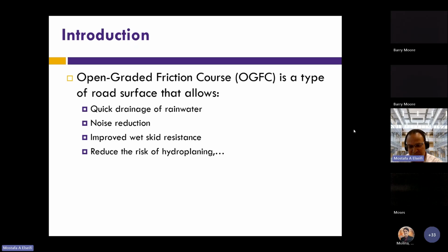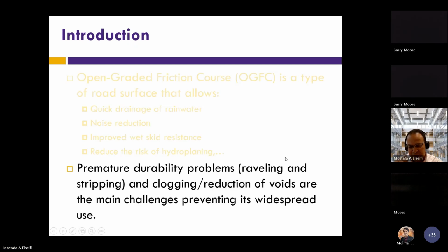However, in terms of performance, it does not last as long as regular dense graded hot mix asphalt. And the reason is that we have a very high air void content. This air void content reduces the film thickness of the binder, which leads to premature raveling and stripping of the mix. Also, the high air void, even though it works very well at the beginning, tends to be clogged with dust and debris over time, which may reduce the permeability of the mix.